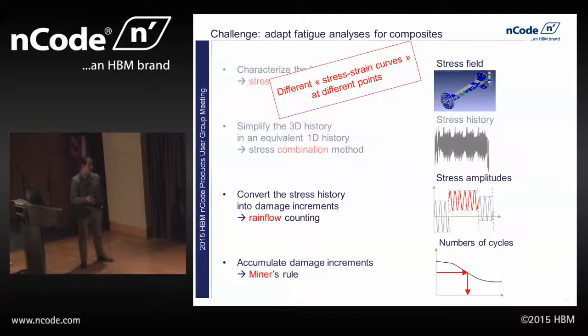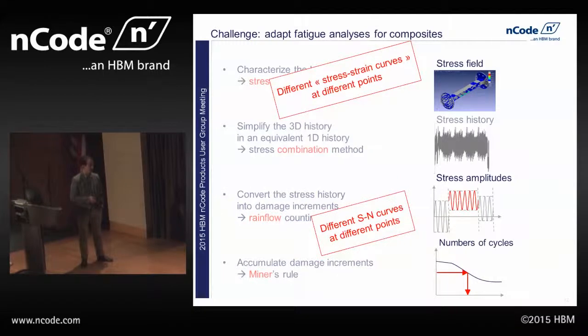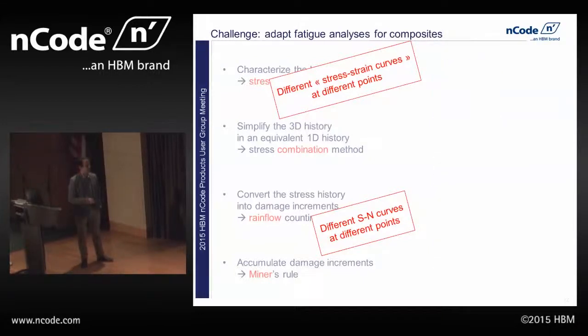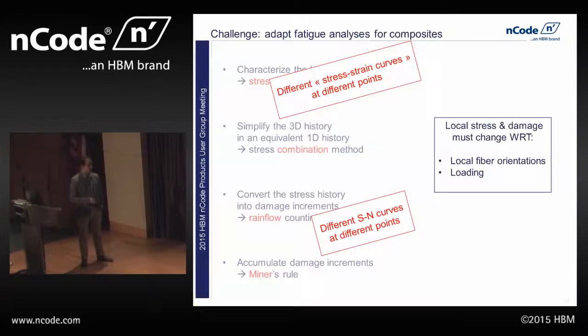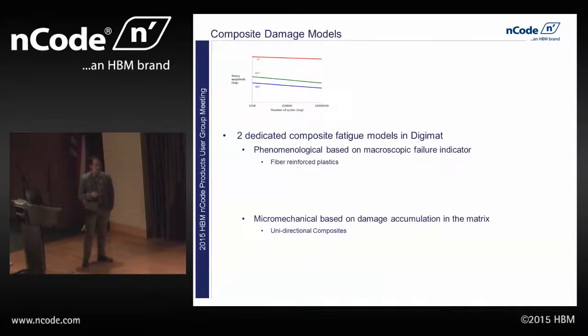And then we need to look at, okay, now that we've actually got our load, how do we figure out what the strength of that is? And then we see our second difference here, which is where we're going to have these different SN curves happening at different points, really driven by that, once again, material heterogeneity. So the takeaway from all this is that our local stress and our damage in our model must change with respect to both our local fiber orientation as well as the load that's being applied to that part. So the way that we're going to handle that inside of Digimat is we're going to use a couple of different damage models.